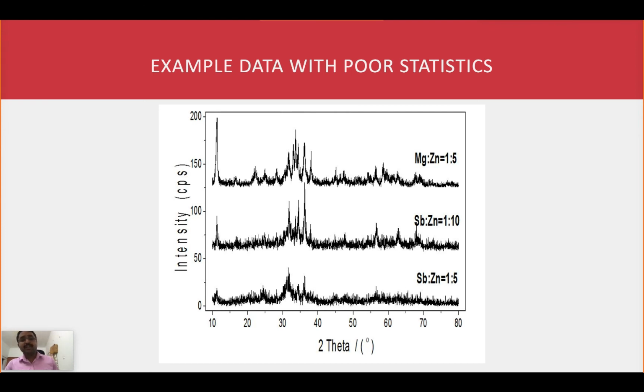It is due to, I can say, 2 or 3 parameters. The main parameter here is that the particular sample is almost amorphous, that is, the degree of crystallinity is very, very less. That is my point of view. So you should be very careful with analyzing these types of samples. So I am giving this as an example of very poor statistics for analyzing your data. So I think this is an amorphous, closely amorphous sample or less degree of crystallinity sample.